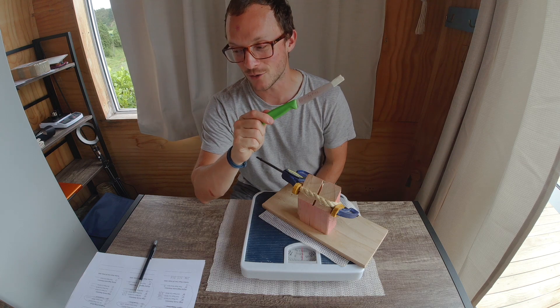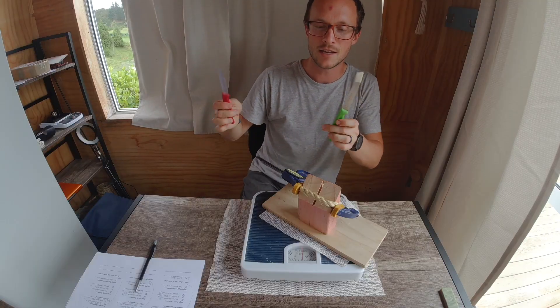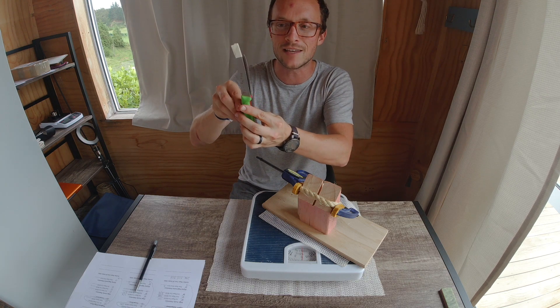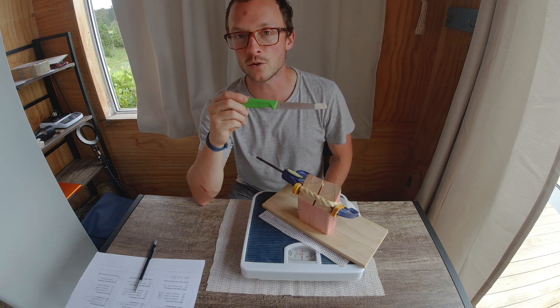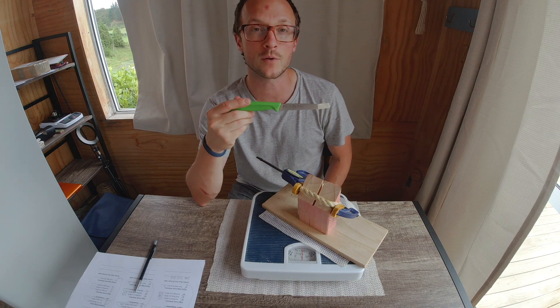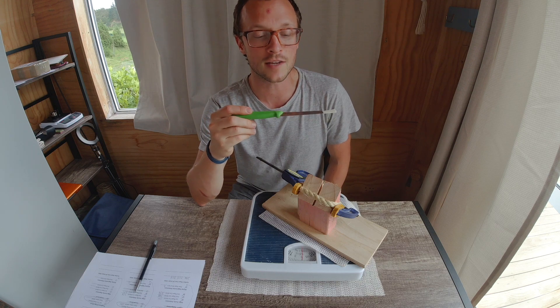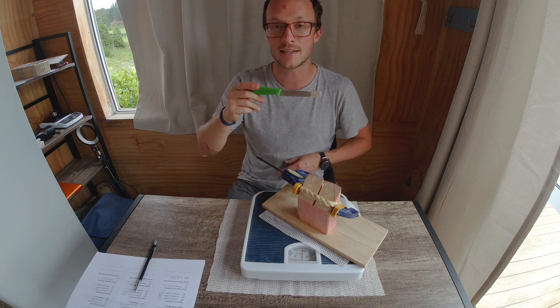This edge actually got down to 140 grams on the BESS machine, but the feeling of aggression is still quite good. The reason we've taped this off is because I don't want any knife to have an advantage in terms of additional edge length, so the edge length is the same as the knives I normally test. This is the second best score on a dual-grit edge I've tested, right after the one sharpened with my original dual-grit method. That edge lasted about 30% longer than any of the fine or coarse edges I've tested so far.